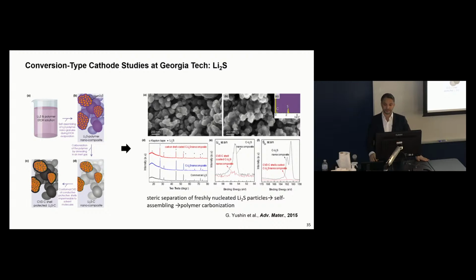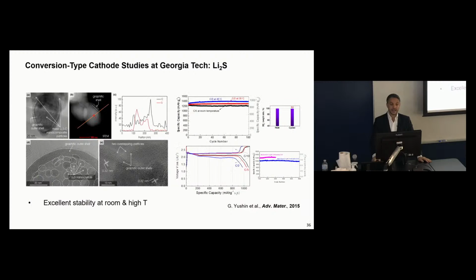And so when you do this process, you can demonstrate that you can produce pure lithium sulfide and carbon composites without anything else, without any side products. And if you do microscopy, you can demonstrate that, yes, you produce what you planned to produce. In this case, we demonstrate these relatively small particles, sub-100 nanometer dimensions, but they comprise even smaller particles of lithium sulfide embedded in this carbon matrix and further protected with this outer graphitic shell.